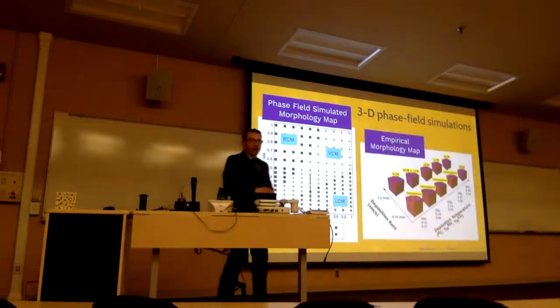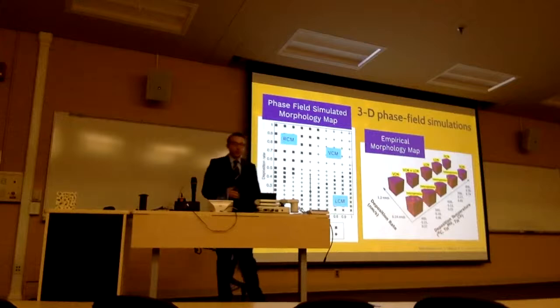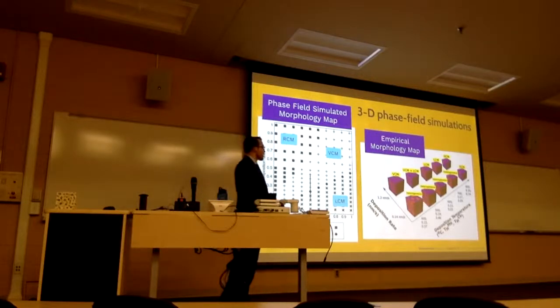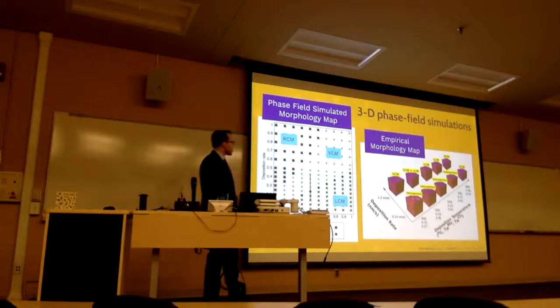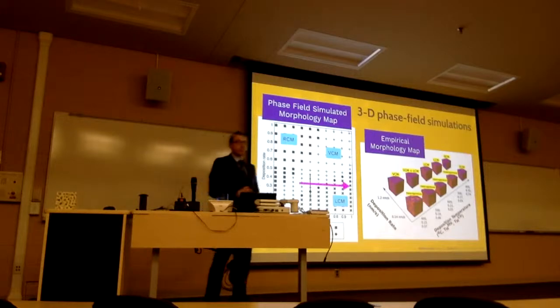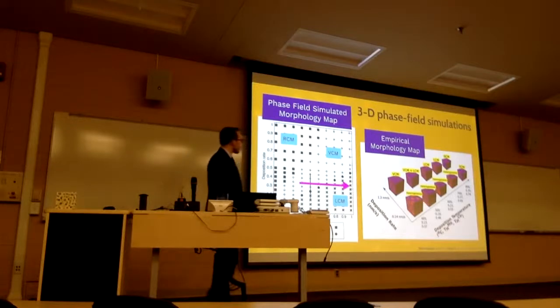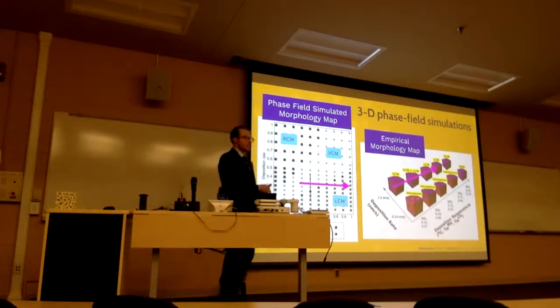And we actually applied all of our empirical results onto our own morphology map, which is a function of deposition rate and deposition temperature. You can see those morphologies labeled here. And our results actually match up very, very well. If you just follow at one deposition rate, increasing the temperature, which increases the mobility of the constituents, you can see agreement with our empirical or experimental results. Now this plot was only made for a certain set of mobilities, but we actually simulated mobilities much greater than that, which predicts this RCM structure. It's just not included in this plot.